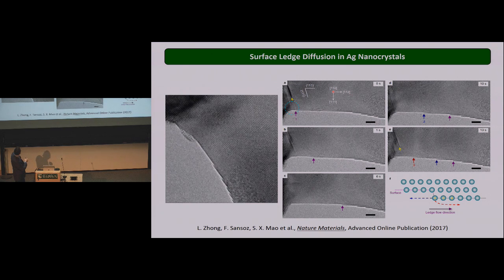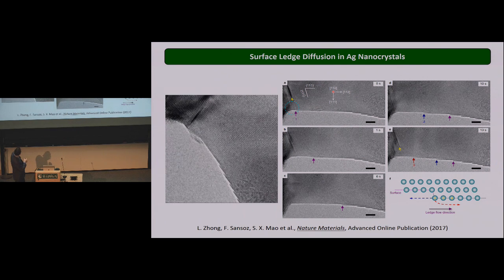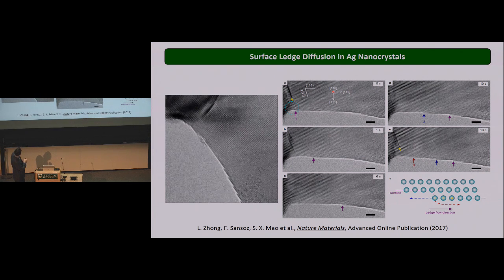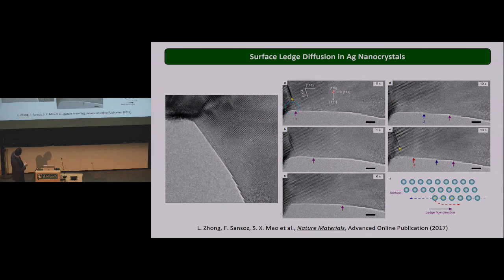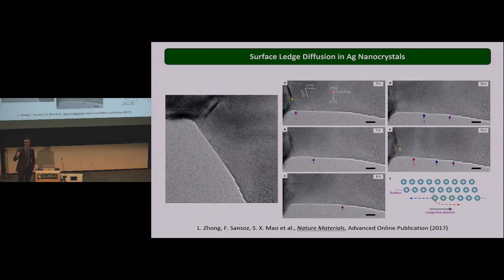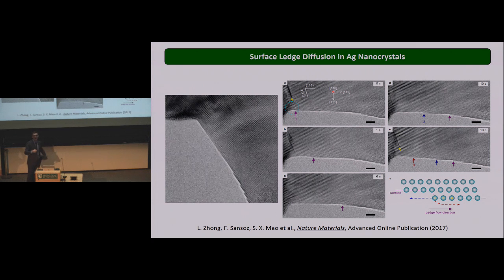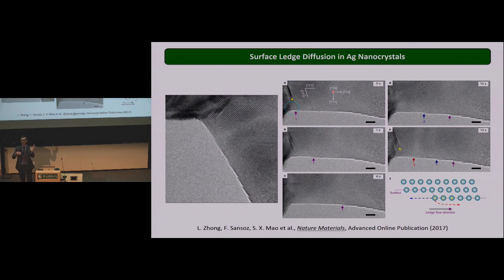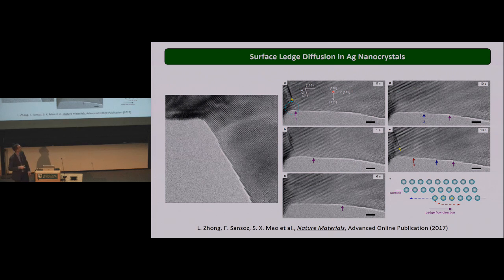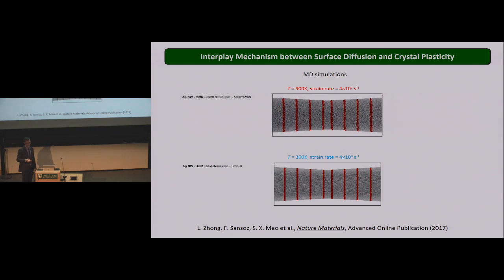So this is very fast dislocation nucleation, so we didn't see the nucleation. You see the steps here that nucleate, like here's a dislocation there, and they form steps, and now those steps are just migrating along this surface. So that suggests here that it's not only crystal slip, it's not just pure diffusion. It looks like it's an interplay. There's crystal slip, and there's some diffusion happening at the same time. All right? So that's the behavior.